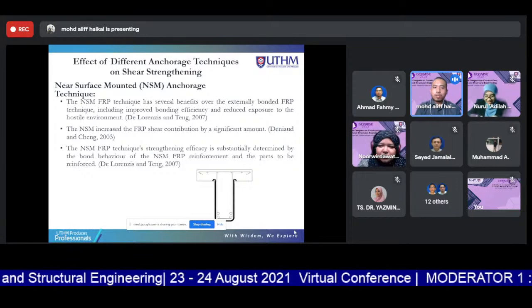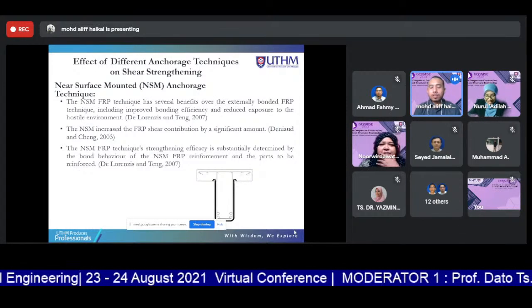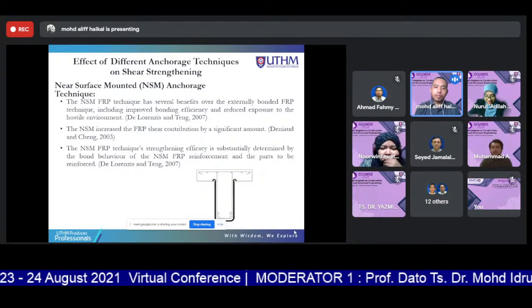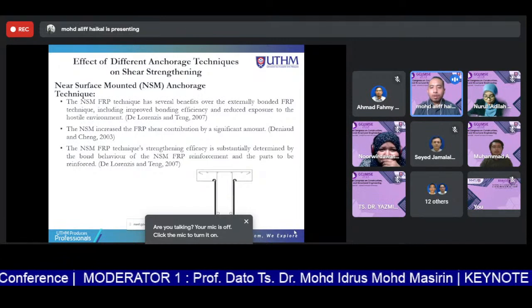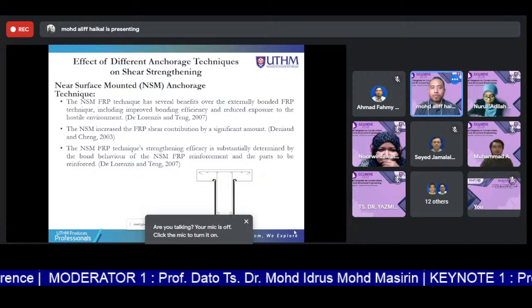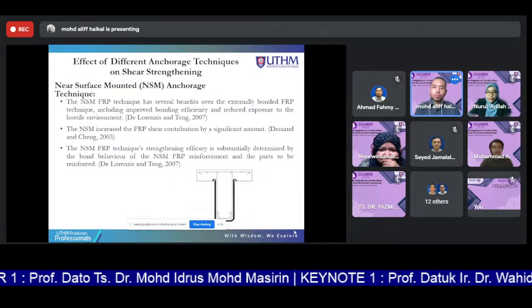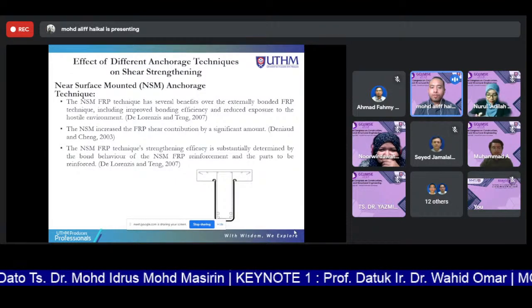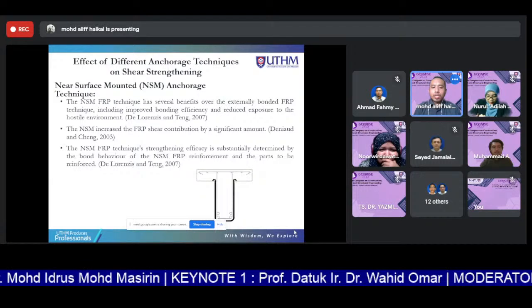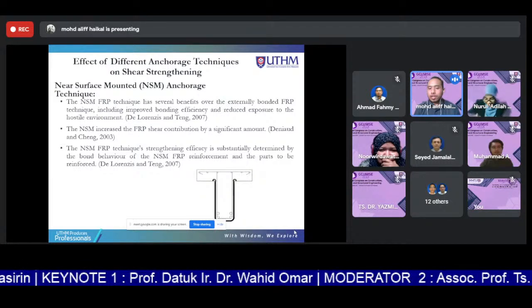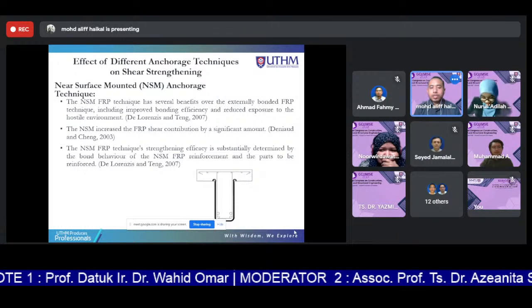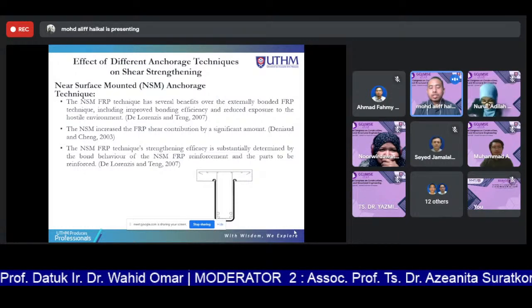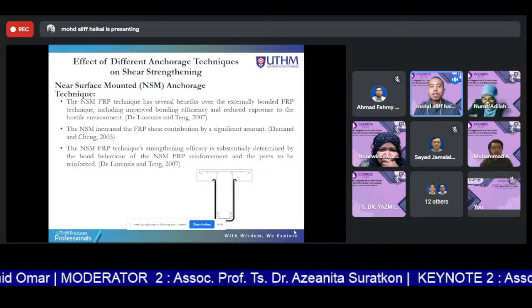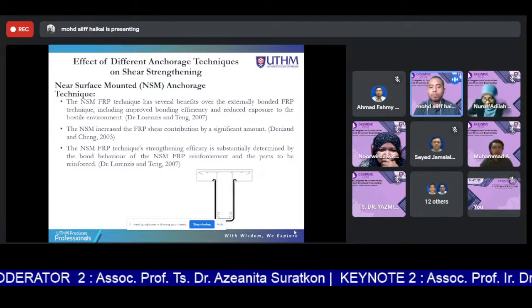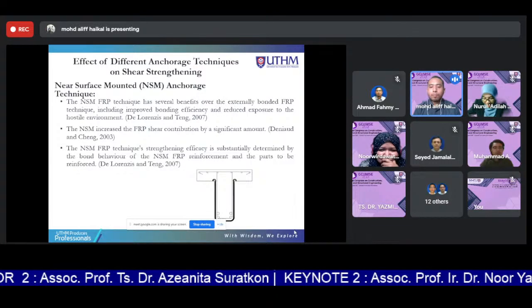Okay, this is the effect of different anchorage techniques on shear strengthening. The first one is the near surface mounted (NSM) anchorage technique. The NSM FRP technique has several benefits over the externally bonded FRP technique, including improved bonding efficiency and reduced exposure to the hostile environment. The NSM increased the FRP shear contribution by a significant amount, and the NSM FRP strengthening efficiency is substantially determined by the bond behavior of the NSM FRP reinforcement and the part to be reinforced.